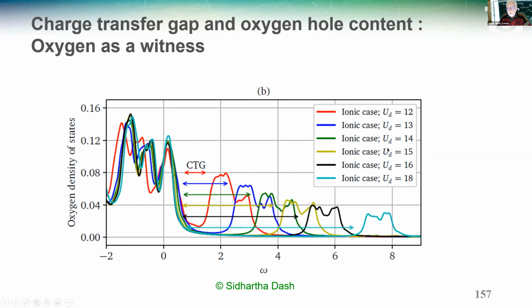Now, every color here corresponds to different values of U. And the largest value of U here is, for example, this value. So you see that the largest value of U has the smallest oxygen hole content. Why is that? Because everything that's above 0 here, if you want, are holes, right? Because it's the states below 0 that are occupied. So large charge transfer gap corresponds to small oxygen hole content.